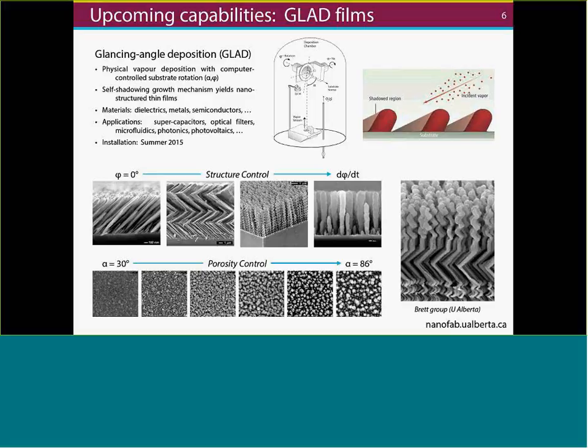Now, one unique capability, which is also coming online within a few months, is that of glancing angle deposition. These are GLAD films. Now, these are a couple of systems which were recently acquired, inherited from the group of Brett at the University of Alberta, who's recently retired. So imagine a standard electron beam evaporator, but instead of placing your substrate horizontally, you place it at a really oblique glancing angle to the vapor flux. You get a self-shadowed growth mechanism for the film. Now, what that enables you to do is, by just choice of both this angle, substrate angle alpha, and also the substrate rotation phi, you're able to tune the nanostructures of the film.